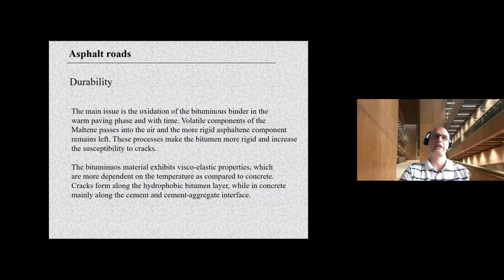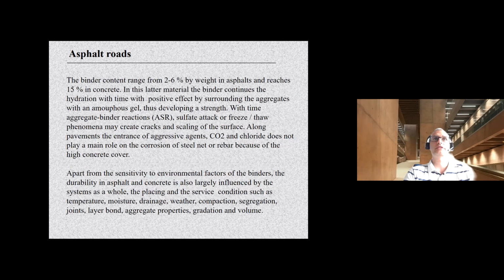The bituminous binder systems actually exhibit viscoelastic property. They are also more dependent on the temperature as compared to concrete. And sometimes the cracks form along the hydrophobic bitumen layer, while in concrete, the main crack formation is actually located in the weakest part of the material, which is the cement paste or the cement aggregate interface. Just to give you an idea of the binder content, in asphalt the organic binder content ranges between 2 and 6% by weight. In concrete, it reaches up to 15% by weight.